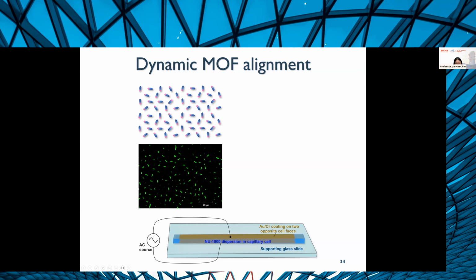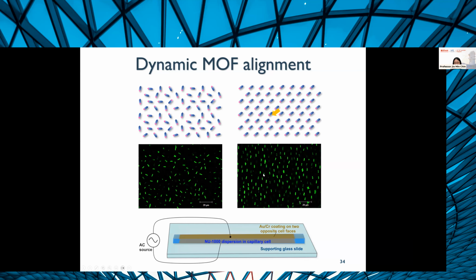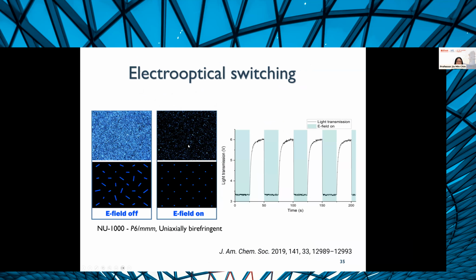Now, if you then have this suspension and you put it inside a capillary and you expose it to an electric field, you very rapidly create not just particles with positional order, but also directional order. And you have these pictures that you see. This can also be observed under polarized optical microscopy. So you have two cross polarizers. And because NU1000 happens to be birefringent, if you look at it through cross polarizers, you will see your MOF particle as a bright spot. And this here at the bottom is just a drawing. This is the real image that we see in the polarized microscope.